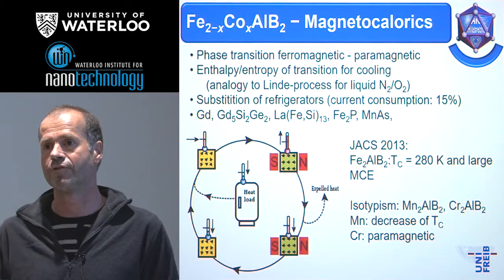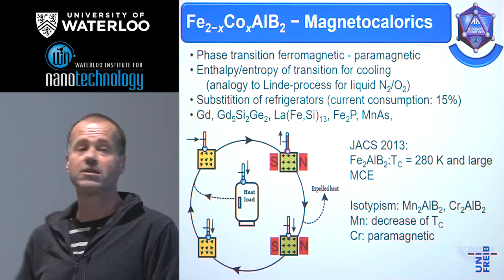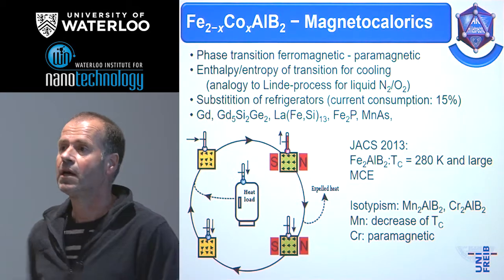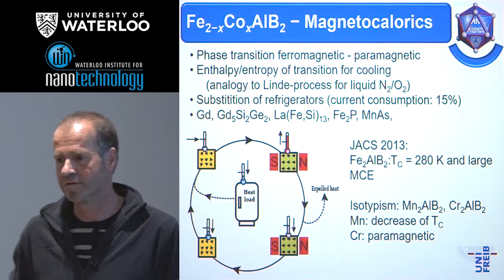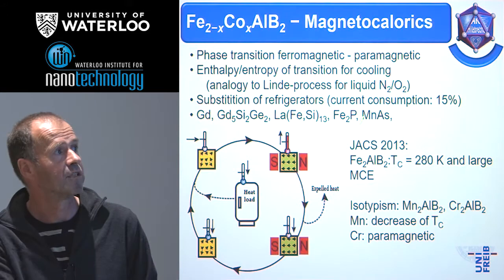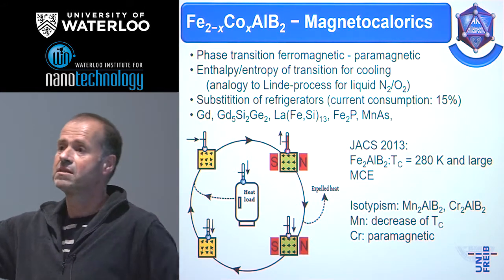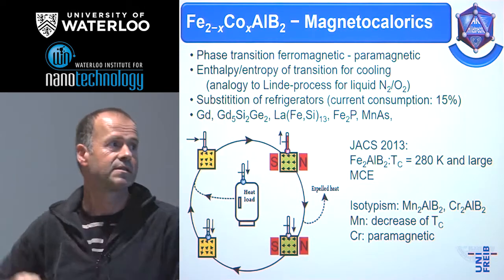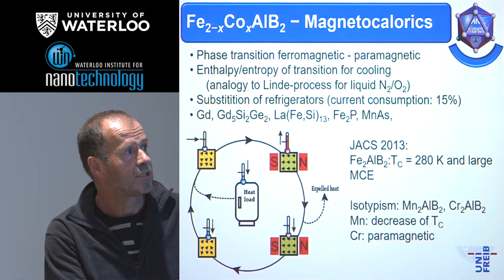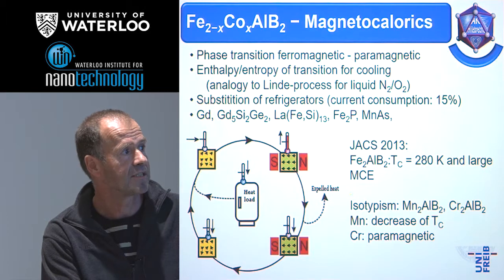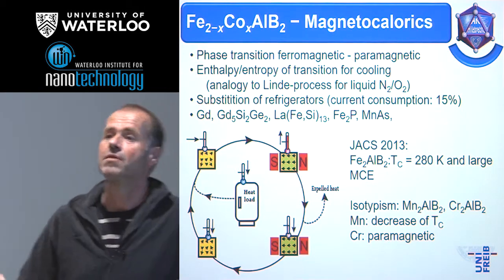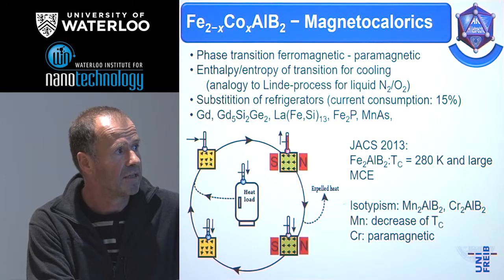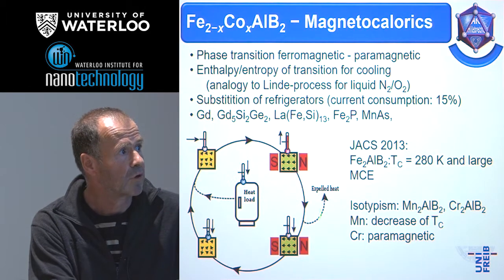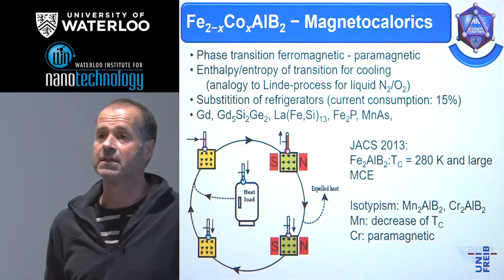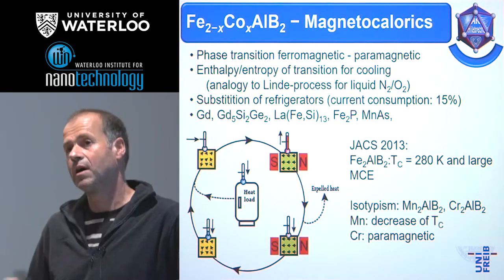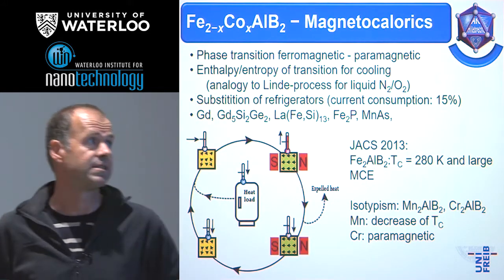And you can use the transition of a ferromagnetic material for cooling devices, like you know it from the Linde process to liquefy the air and separate nitrogen and oxygen. So you do a cycled process where you combine a heating step and a cooling step. That means the energy which is produced by the phase transition can be put outside of the system, and if you relax the system, it takes the energy or the heat you have taken out from itself, so it cools down. And if you combine these two processes, it's possible to build a cooling device which has a comparable efficiency as we get with the thermoelectric or Peltier systems.